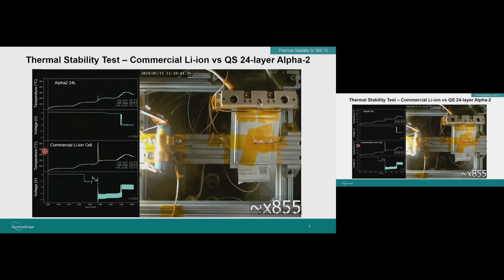What you'll see right here is a standard automotive test that is used to qualify batteries before they're allowed to go into vehicles. What happens is you put a battery inside a thermal chamber and heat it up in various stages until about 200 degrees C. And at that point, basically all lithium-ion batteries will have failed by the time they reach 200 degrees C. So that's where the official test ends. We modified this test to go up to 300 degrees C.